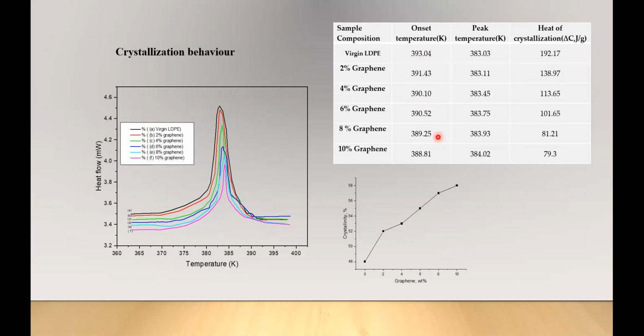Nucleation means the ability to crystallize from the liquid phase. The onset temperature usually indicates the beginning of the crystallization process, and the maximum of the exothermic peak indicates the occurrence of spherulite impingement. The increase of peak crystallization temperature of the LDPE with the increasing concentration of graphene powder suggests that the crystal growth of LDPE in the composite would take place at higher temperature, leading to larger crystalline size, improved crystal perfection and narrower crystal size distribution.